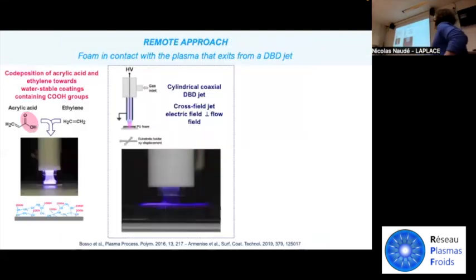Let me just very briefly mention another study we did, just to explore the potential, because, as you know, there are limitations in the gas gap thickness at atmospheric pressure. At least with the expertise we have in Bari on power supply, we were able to easily obtain the helium plasma within a 5 millimeter thick foam.